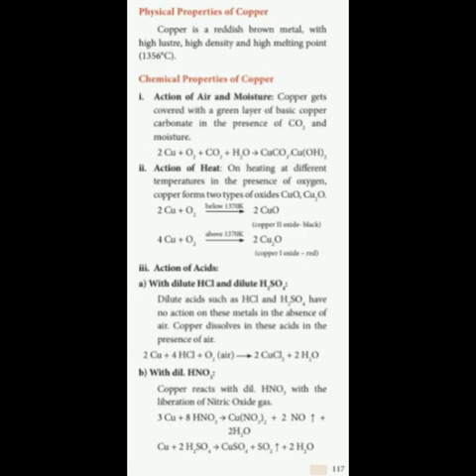The next chemical property is action of heat — a very important question. When copper is heated below 1370 K in the presence of oxygen, it forms copper oxide (CuO), which is black in color (cupric oxide). When copper is heated above 1370 K, it forms red cuprous oxide (Cu₂O). So at two different temperatures, copper reacts with oxygen to form different oxides: black cupric oxide and red cuprous oxide.